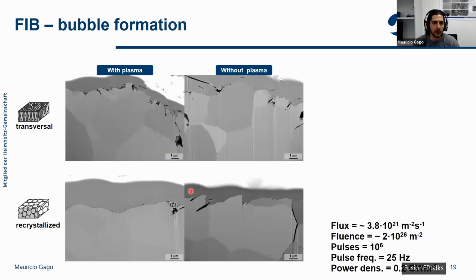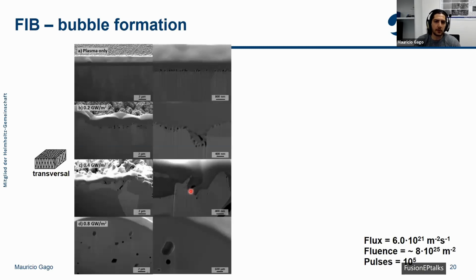And as we will see later, in the samples exposed to 1,000,000 pulses, we also don't see any bubble formation here. This bubble formation we only start seeing at higher power loads. So at 0.2 gigawatts per square meter, we see no real bubble formation. Here we see only some of the fuzz that has been formed. At 0.4 gigawatts per square meter, we already see small bubbles being formed on the surface, but they're not really that significant. And then only at the highest power load, which is close to the power load expected for ELMs right now in ITER, we see a significant bubble formation and also the bubbles being coalesced, and that's why they have a higher size.